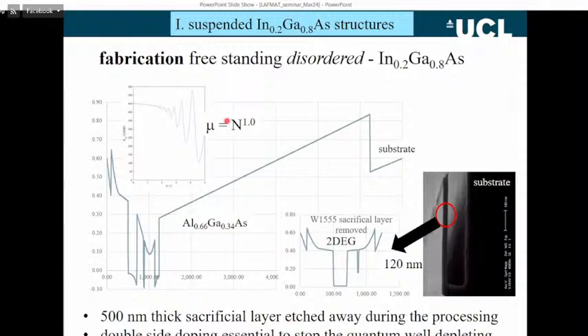So what we did to advance this project is, instead of having these graded layers between the substrate and the two-dimensional quantum well, we purposely put in a sacrificial layer. So this diagram here shows the confinement potential as a function of thickness. This is the surface. We've then got the quantum well made of gallium arsenide. We've then got other structures here. We've got buffer layers, we've got doping. We've then got this thick sacrificial layer made of aluminium gallium arsenide, and it's 66% aluminium gallium arsenide, and that's very, very reactive. When we put this structure into HF acid, the HF acid attacks preferentially this sacrificial layer.